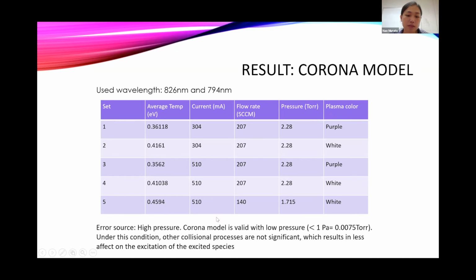However, corona model is valid only with low pressure, lower than 0.0075 torr. And under this condition, other collisional processes are not significant, which result in less effect on the excitation of the excited species. So we use extremely high pressure compared to this condition. So that's why we got the lower temperature than we expected.